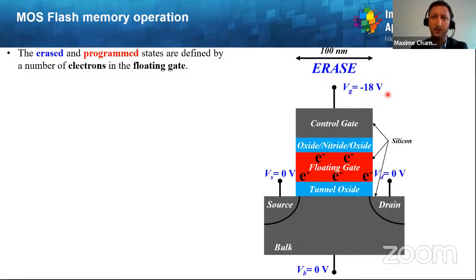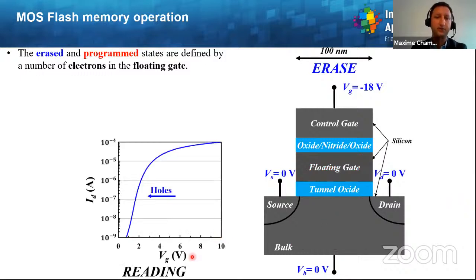For erasing the flash memory, one can use a negative voltage here and zero elsewhere, and the electrons will be repelled towards the bulk, so the silicon substrate. Afterwards, one can read the drain current as a function of the gate voltage, which is nothing else than a characteristic curve for stating 0 or 1 for the logical state of the device. And then if one wants to program the flash memory, you put 0 volts in the source and the bulk, and then a positive voltage to the drain and the control gate.